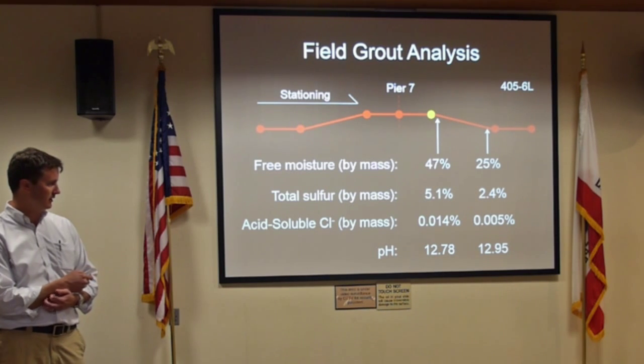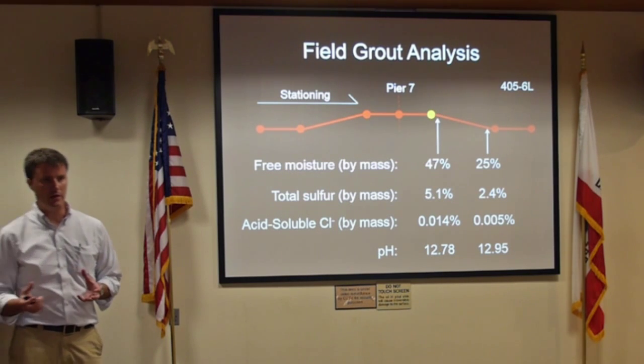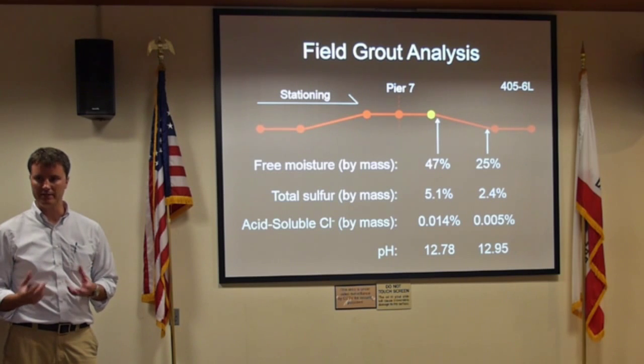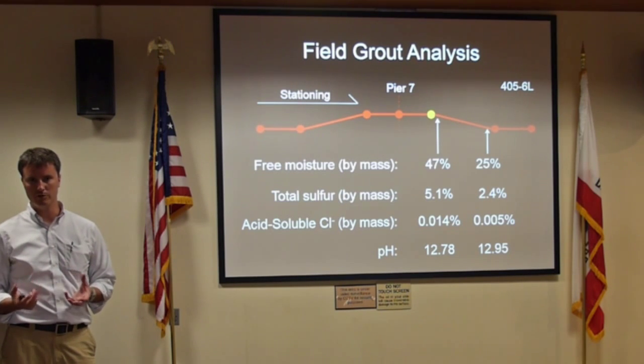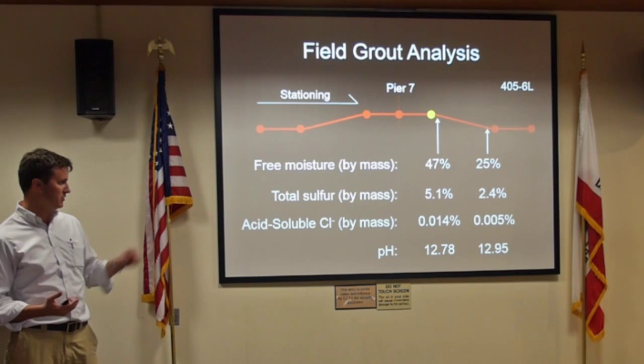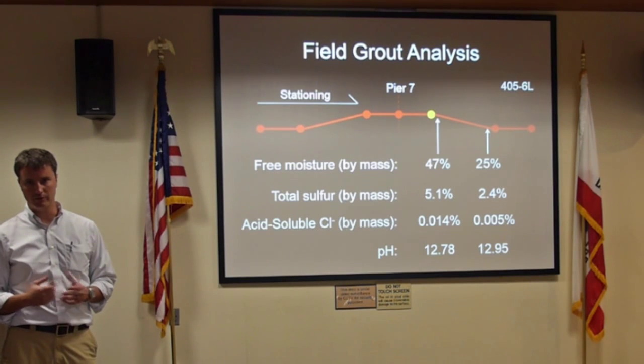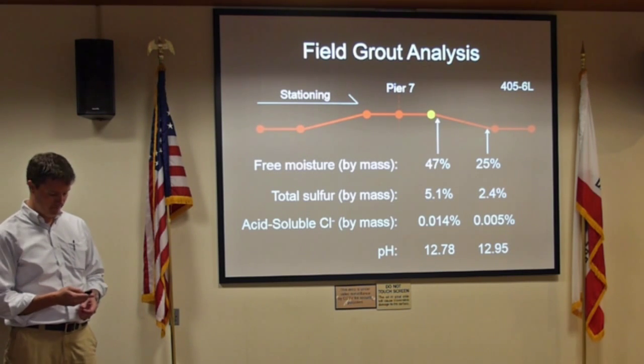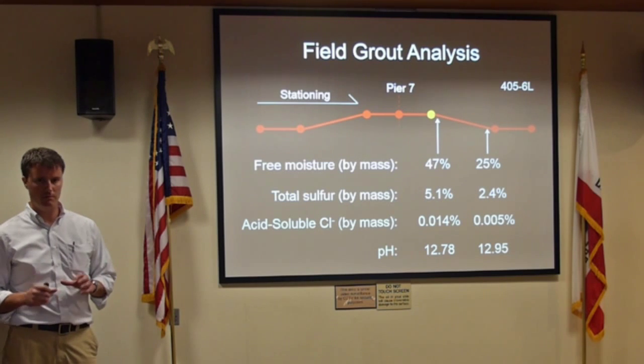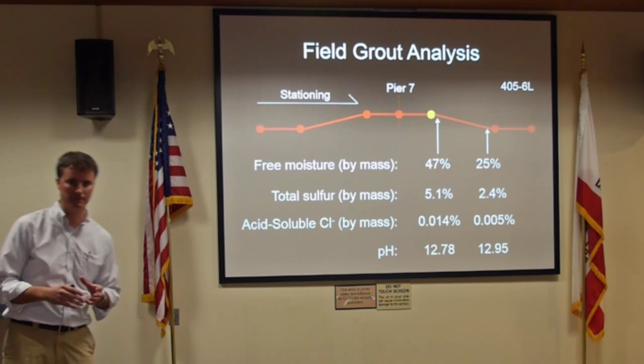And then the other interesting thing is that steel in a high pH environment is generally pretty happy. It's what's called passivated. You generally don't have corrosion, but in this case, very aggressive corrosion, but you still have the high pH environment, so that's a little bit of a head scratcher. But what we found is that essentially you had a segregation of material.